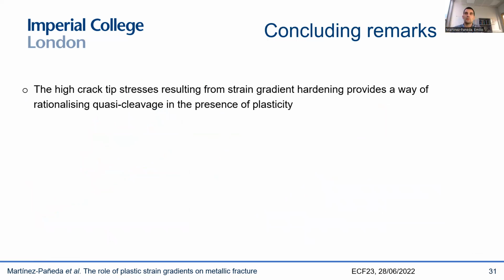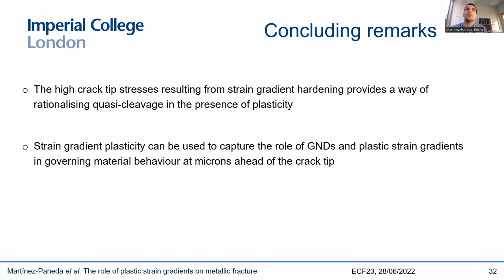So that takes me to the concluding remarks, hopefully leaving a bit of time for questions. I just want to emphasize 3 takeaway points. The first one is that we believe that we have a hypothesis to understand why brittle fracture is often observed in the presence of significant plastic flow. And this is that we have very high crack tip stresses that are a result of the strain gradient hardening that arises due to the presence of GNDs and plastic strain gradients. And this is something that we can capture using strain gradient plasticity models.